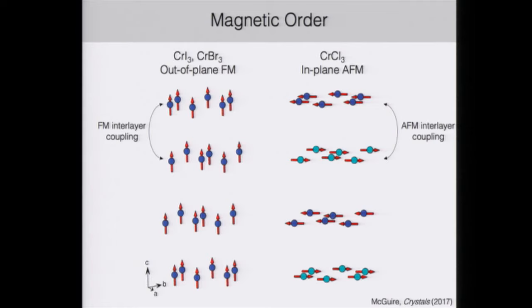In chromium iodide and chromium bromide, there's out-of-plane ferromagnetism. Within each layer, the spins point perpendicularly out of the plane, and then the ferromagnetic interlayer coupling gives a net ferromagnetic moment. In contrast, chromium trichloride is an in-plane antiferromagnet. Within each layer, the spins order in-plane ferromagnetically, but then antiferromagnetic interlayer coupling across the van der Waals gap gives rise to no net moment overall and antiferromagnetic behavior.